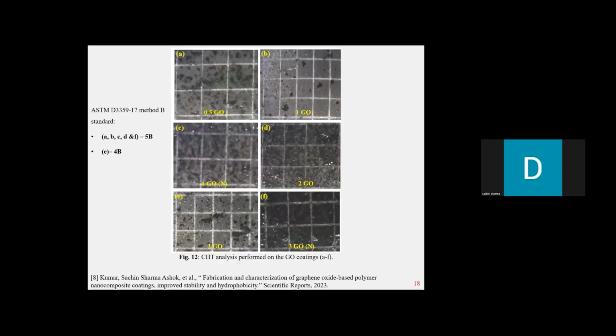So now when we have already evaluated the water contact angle and the EIS, now it's very important to know whether our coatings are intact or not, whether there are any cracks, any holes, and so on. So all the coatings were subjected to the crosshatch tests with respect to the ASTM D3359-17 method B standard.